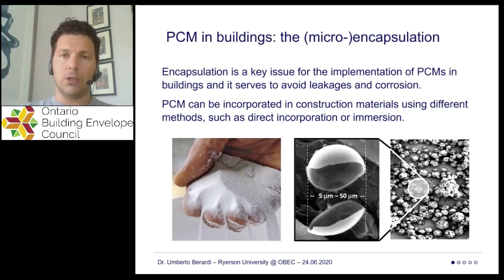So typically on the market, you can find a lot of powders of PCMs that are really surrounded by a polymer. So at the end of the day, you are using nothing more than a sand, or something that looks like sand. But if you use a microscope and zoom in, this granular powder is really encapsulating a PCM in the middle. And so the PCM can melt and solidify, and this process may accumulate or release energy. Meanwhile, it's stabilizing your internal temperature in the building, and can be your thermal battery, although it's pretty lightweight and not really increasing the weight of your facade too much.